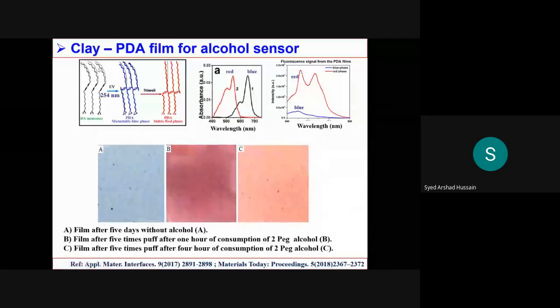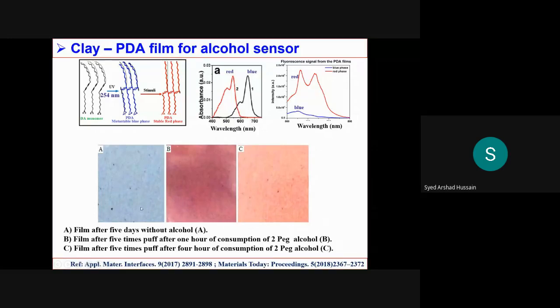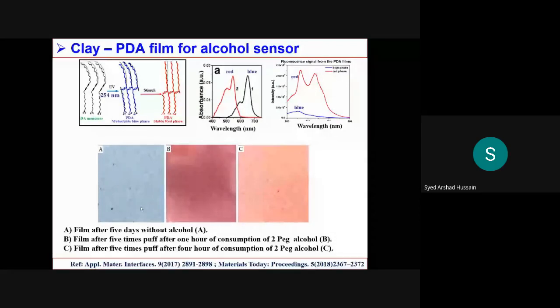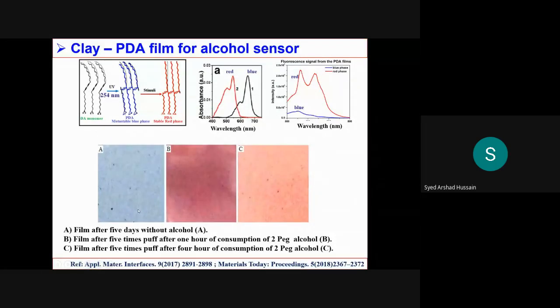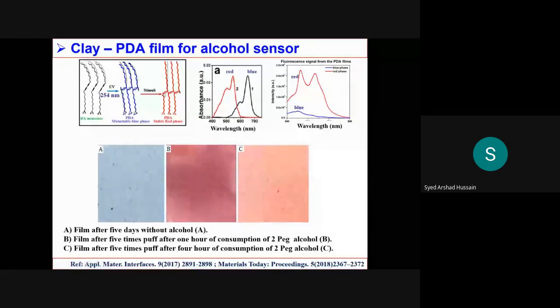We prepare the film using self-standing systems, and this image is recorded using just a simple camera. First, we exposed the system to UV and transferred it into the blue phase. Then you can see this image A. This is just the blue phase image recorded. Then we expose this film to alcohol, and you can see the color change. In the presence of alcohol, the PDA phase changes from blue to red, and this color change is observed by naked eye. And the first image, you see the film after 5 puffs, 1 hour after consumption of 2 Peg alcohol.